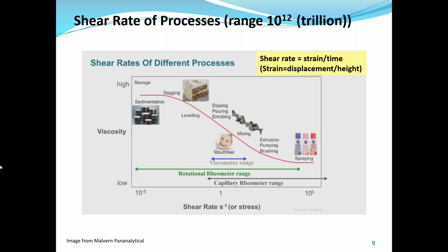I think they're probably for butter pretty similar. Certainly the data will tell you. I think that maybe going with a height would probably be the most straightforward. So between 0.2 and 1 millimeter would be fine. But it certainly would not be bad to look at gapping your butter at 5 degrees using different forces, going down to a fraction of a newton up to, at least with the Malvern connections, up to 40 newtons. So that'd be an interesting study to do.